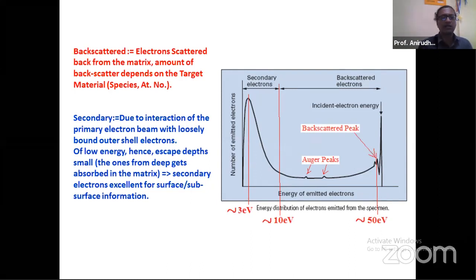So backscattered electrons are electrons scattered back from the matrix. That means they impinge and then they deflect back. The amount of deflection back is because now they go and hit against the target and are reflected back. This interaction would depend on the target nucleus. Therefore, those electrons are called backscattered because they get backscattered when they hit a species or an atom. So the amount of backscatter depends on the material, whether it is carbon or whether it is uranium. You will get two different energies for those backscattered values.